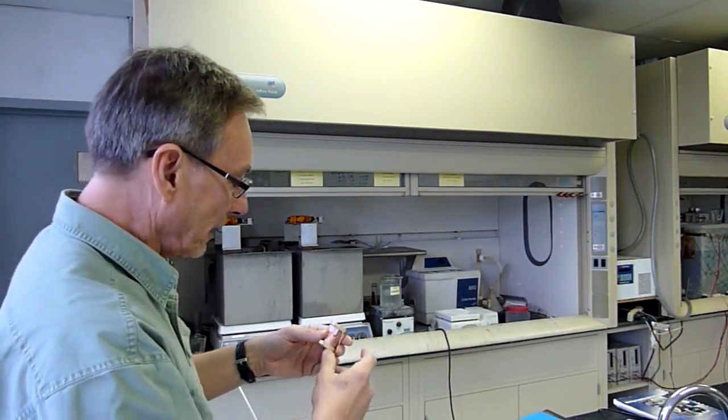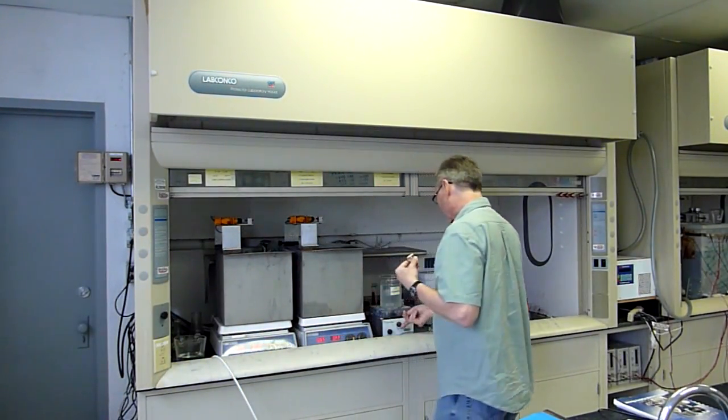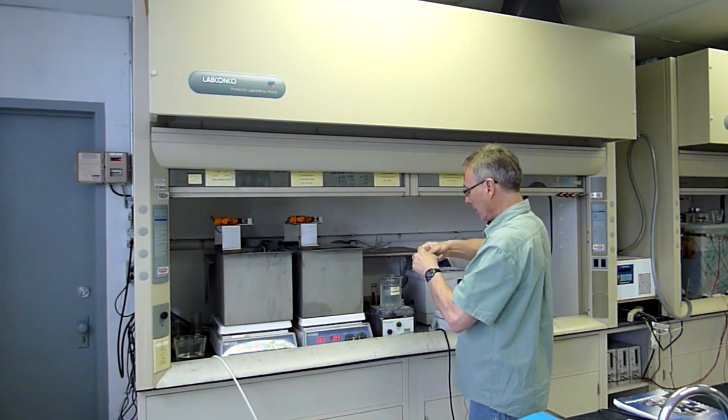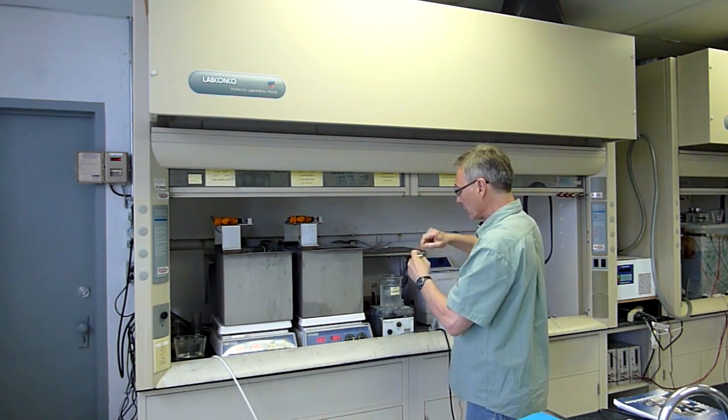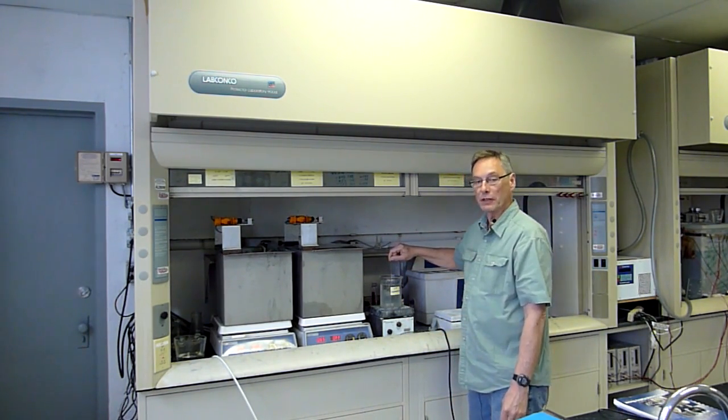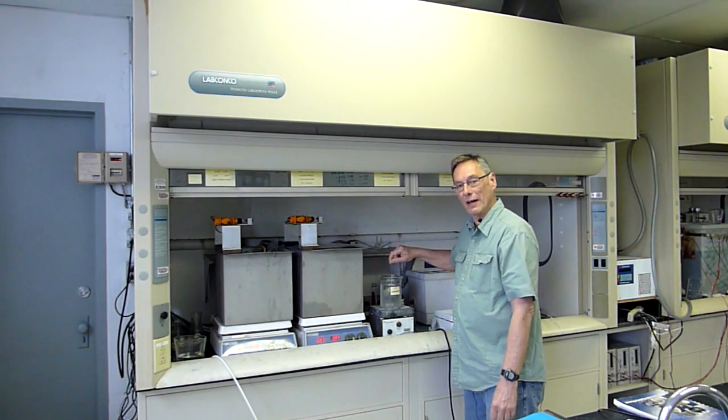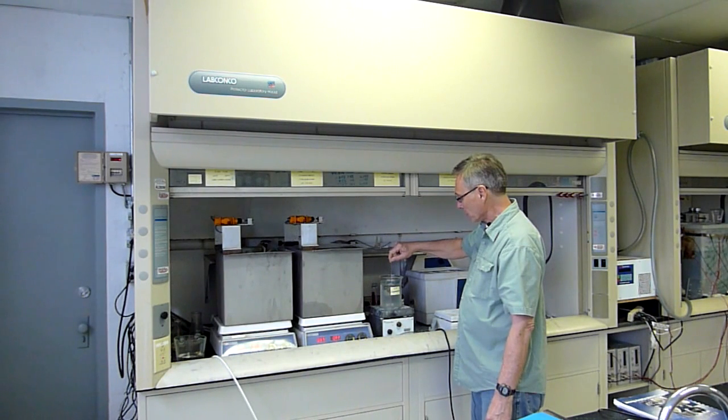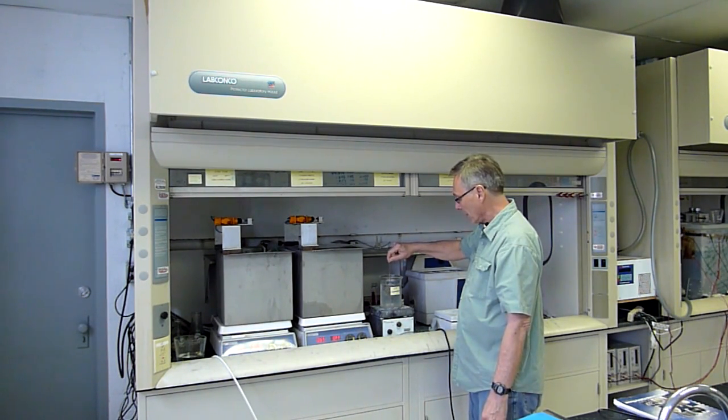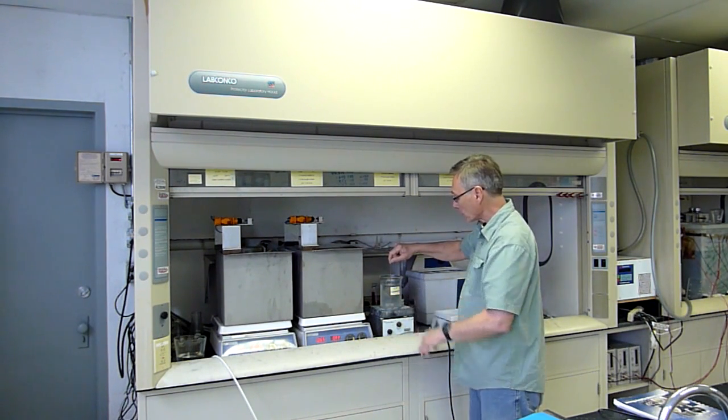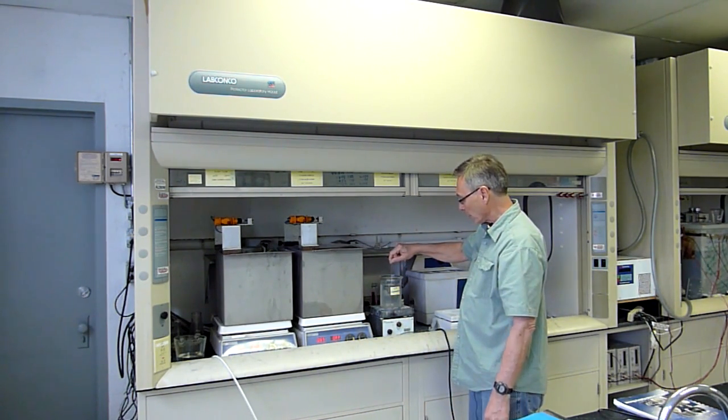So we're going to take this piece over to our gold plating area, and we're going to plate it just like we would any copper or brass piece that's going to get gold plating. We start it out in the SP degreaser. This is a hot dip. It's really just a washing soda solution, an alkali cleaner, but the product we buy is called SP degreaser. That comes from the Caswell plating supply company.